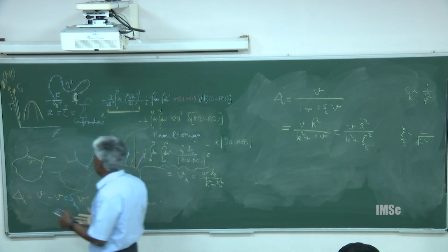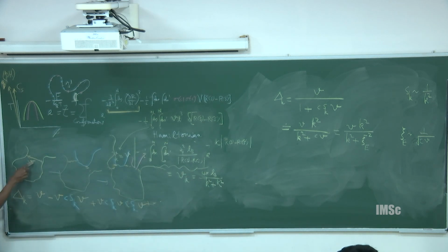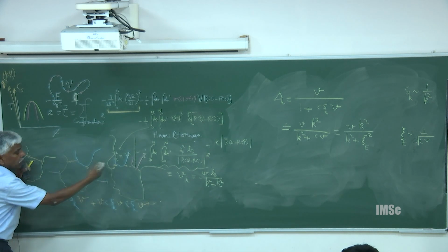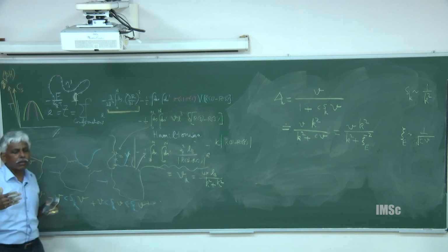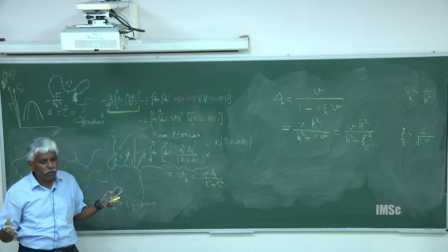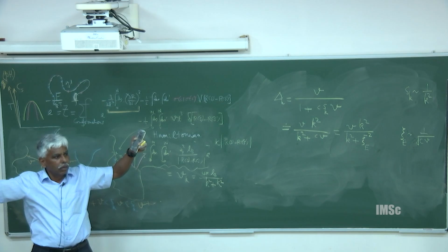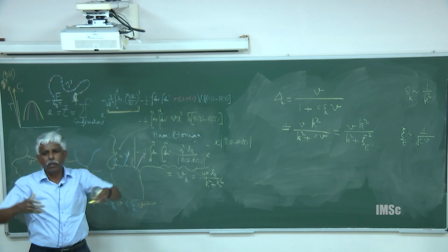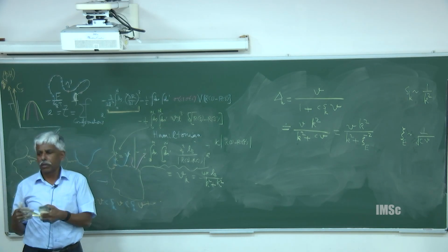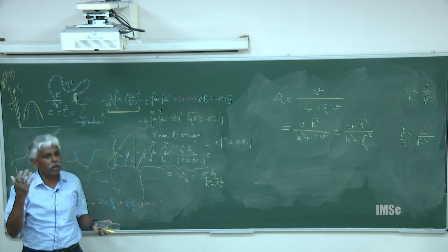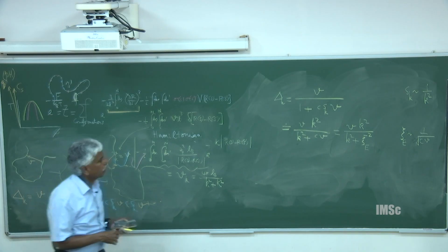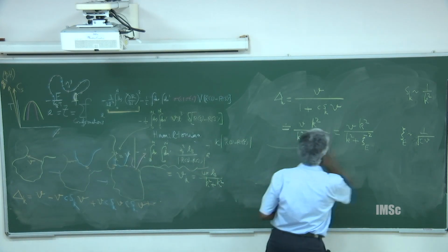The meaning of that is, originally I had this interaction. Because of the interpenetration of the other chains, the net effect is to screen it. Therefore, when you go to higher and higher concentration, although it's a good solution with swollen chains, it becomes like a Gaussian chain because the excluded volume interactions get screened by topological effects. It's called topological screening. Okay, that's for the neutral case.